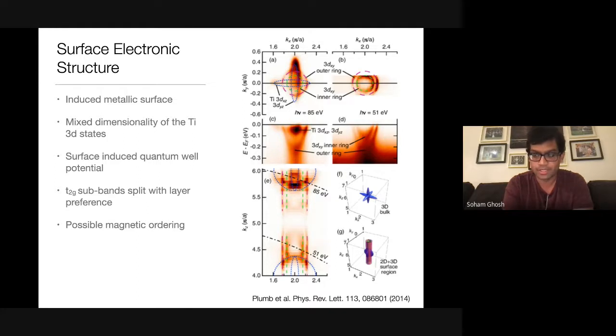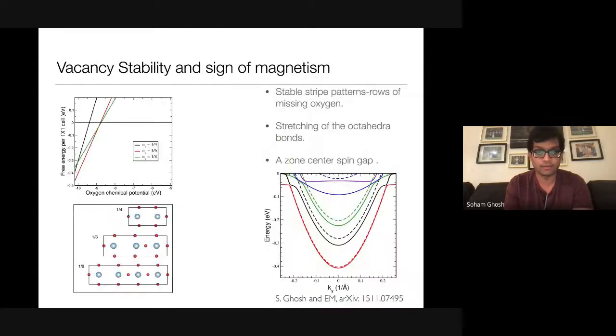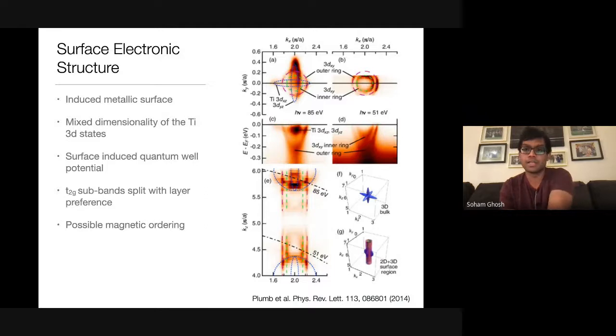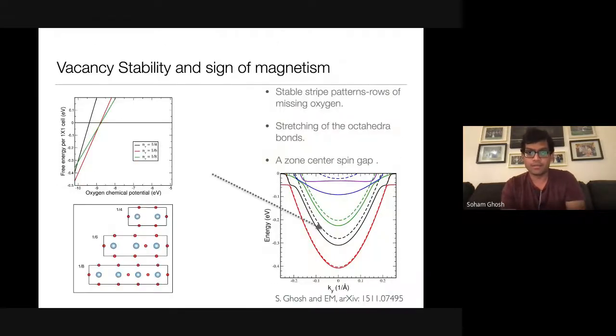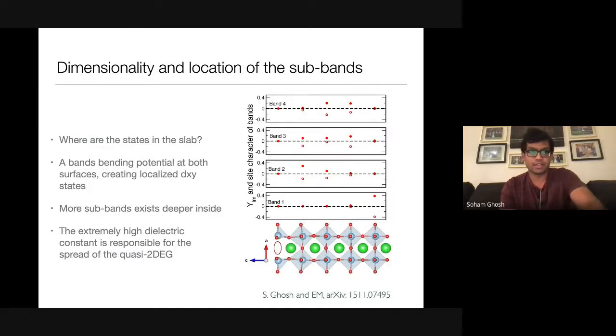So this is an example of how experiments and theory come together. For example, this is a very well-cited experiment from 2014 where they show these same bands using a method called ARPES. So this shows the same bands that we can generate using density functional theory simulations. This also shows that there is spin splitting. And we can also show that. For example, on the left is a picture of the stability of the vacancy oxygens, and on the right is a picture of the bands, this time split in spin. And if you compare these levels with the experiment, you will see that they fall right on top of each other. And not just that, what you also see is that the dimensionality is correct and the location is correct.